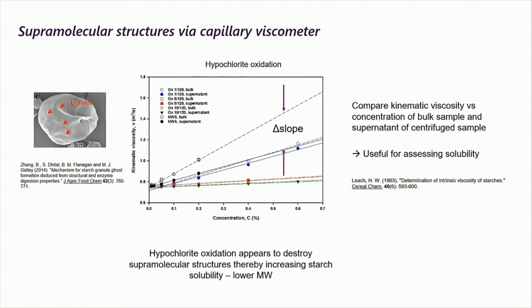A relatively simple way of working out the supramolecular structures, I suppose, is by looking at the kinematic viscosity. What I do is prepare a 2% solution and dilute that to various concentrations, and you just measure the time that it takes to run through a certain size capillary, and you end up with these curves here of kinematic viscosity versus concentration. Now, if you look at the black dotted lines, that's the results for the native wheat starch. You can see there's quite a big gap there.